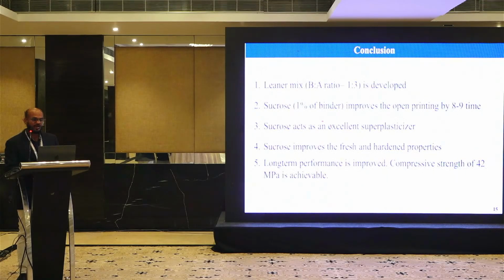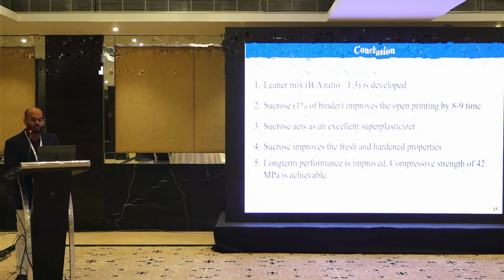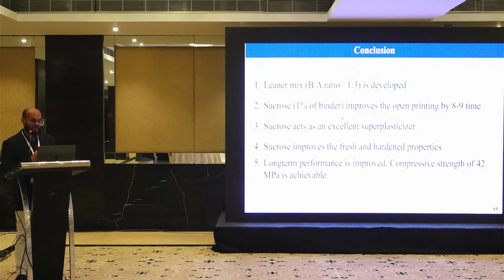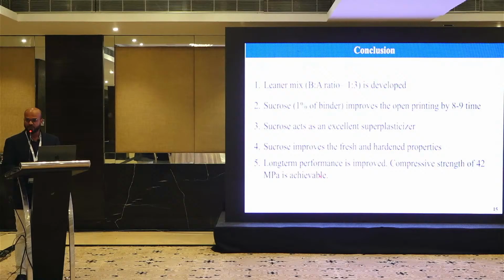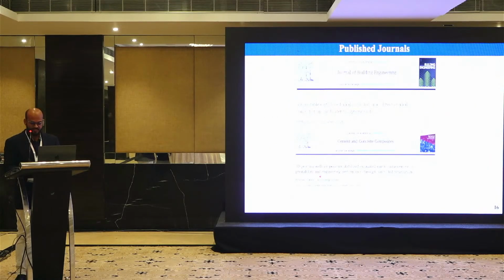And finally, concluding, we successfully developed the earth-based geopolymer material with a lean mix proportion. And sucrose here improves the open printing time. It also performs as a very excellent superplasticizer, meaning it is reducing water. At the same time, it improves the fresh and hardened properties. And further, the long-term performance has also been improved. Thank you very much. And these are my publications.